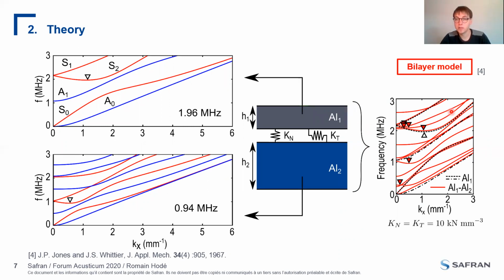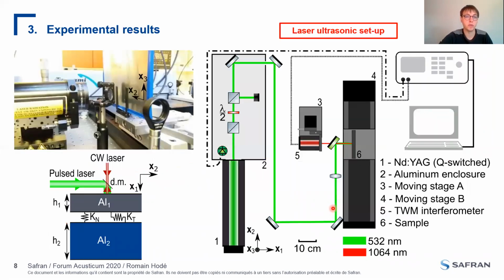And the dispersion curves are plotted in red. And we can see that they are different from the case, for example, of just an aluminum plate in black here with just one ZGV mode. So in the case of a coupling between the two aluminum plates, we will have different ZGV modes and different frequencies. But the goal of this presentation is not to find this value of interfacial stiffnesses, but to study the attenuation of ZGV resonances as a function of time to discriminate the different samples. And now I will talk about what we can obtain experimentally on these samples.